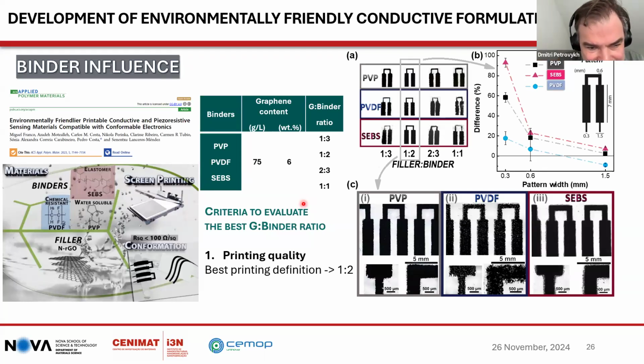Okay. All right. So the next question is, since you selected different graphene oxide ratios for each binder, how did you determine that the mechanically exfoliated graphene oxides exhibit consistent properties across all the different binders that you tried? Because I use a commercial graphene, so the intrinsic properties in this case should be the same. I just changed the ratios, just for information.